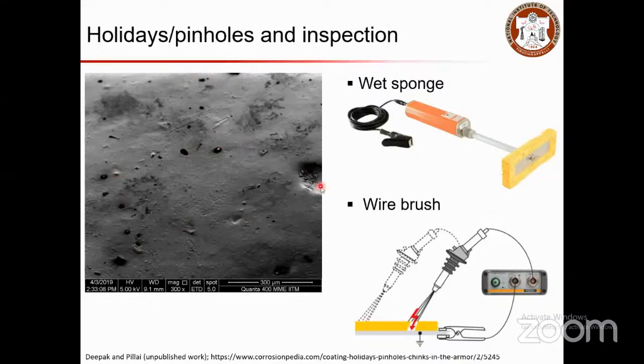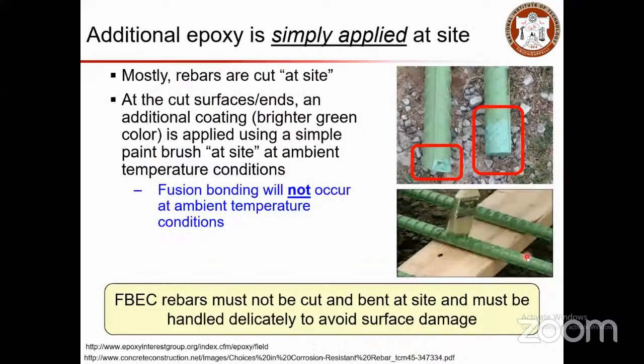So when you do the inspection, how do you do it? You have a wet sponge and a wire brush connected to it, and then you check, and this will indicate the damages on the surface. There are a lot of poor practices that we also observed on site.